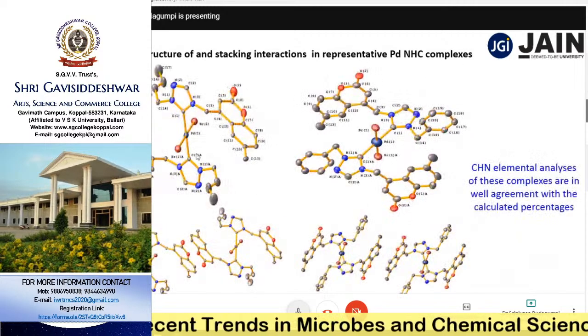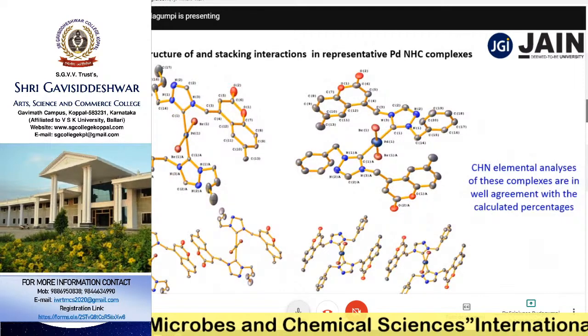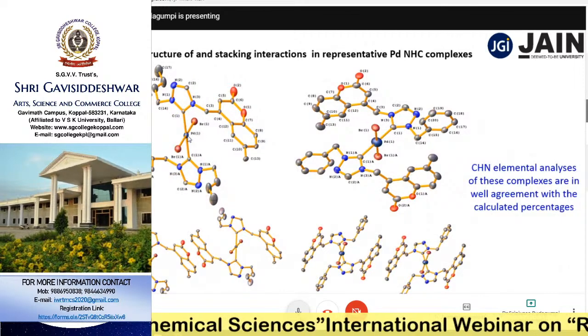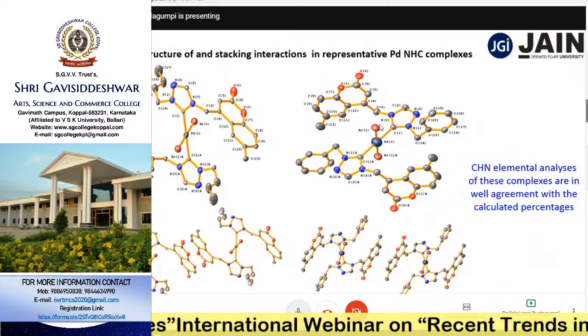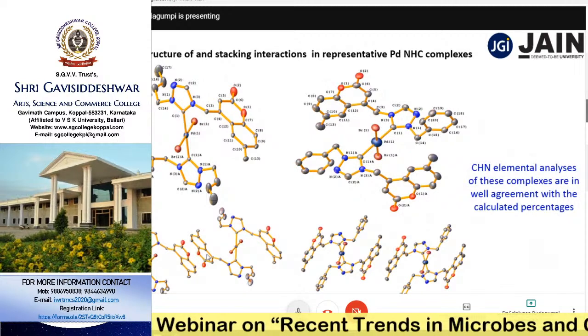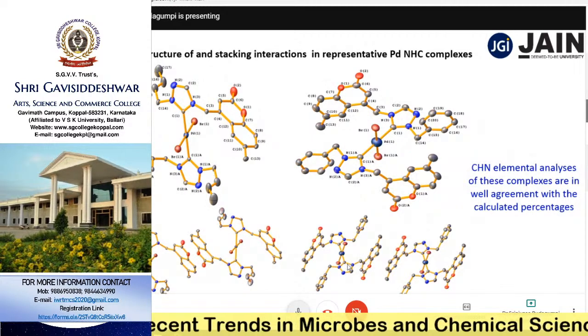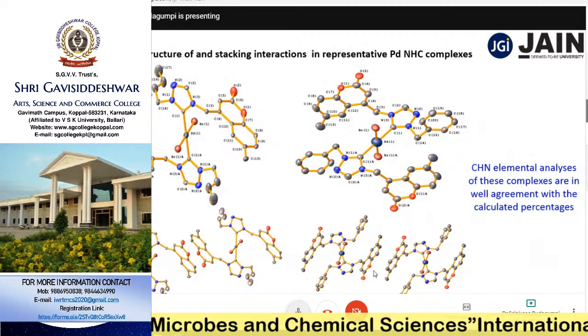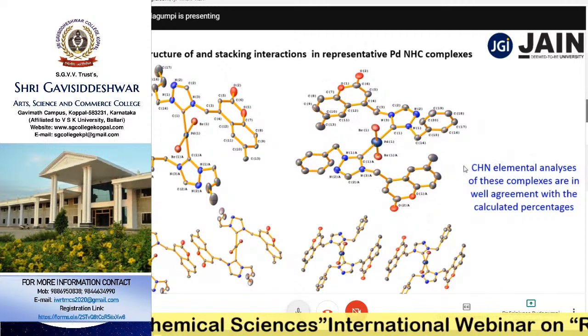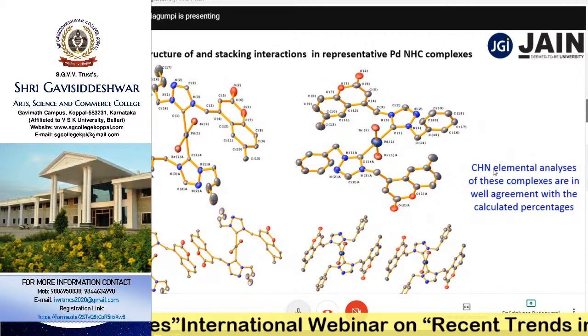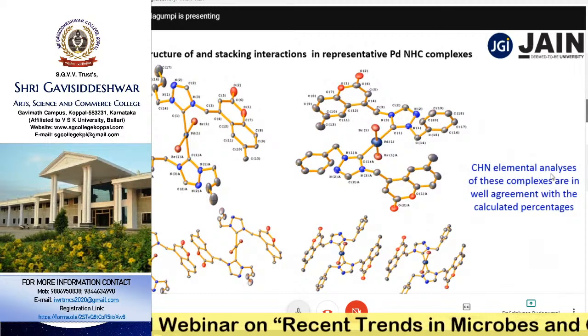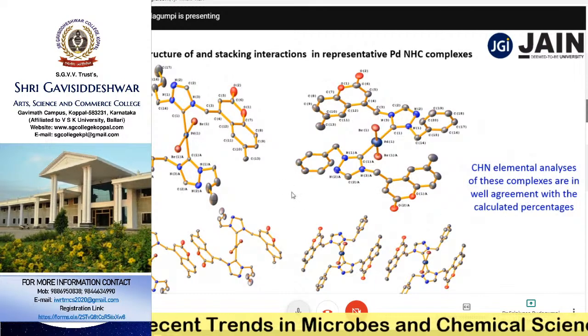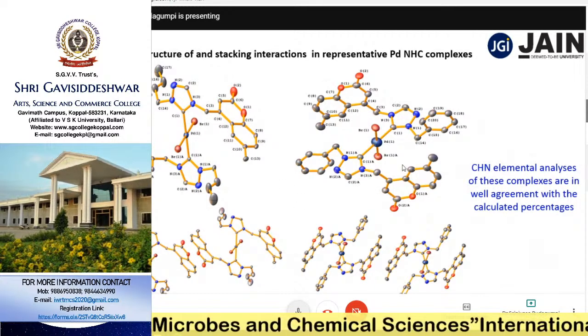Similarly, we were able to get the crystal structure solved for butyl substituted NHC palladium complex and benzyl substituted NHC palladium complex, and all these complexes have displayed pi-pi stacking interactions. Further, all the complexes have also been studied for the structure using CHN elemental analysis, and the results were in good agreement with the calculated CHN percentage.